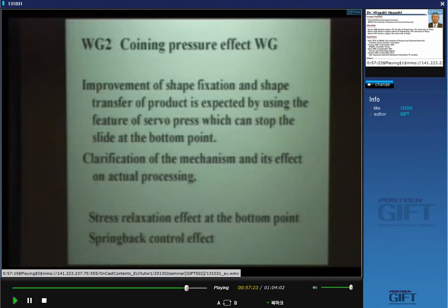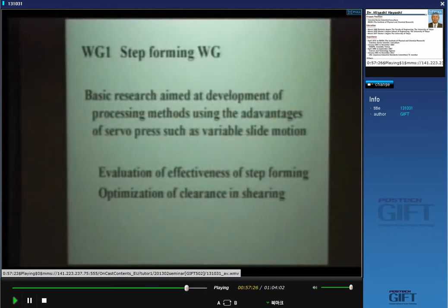And some change of slide motion like this, they applied. Unfortunately, in this working group, they couldn't get very good results. So there were no effects of step forming in the improvement of shearing processes. Perhaps the step forming is good for deep drawing. So at present, in the new joint meeting, they are now investigating the step forming in the deep drawing process.